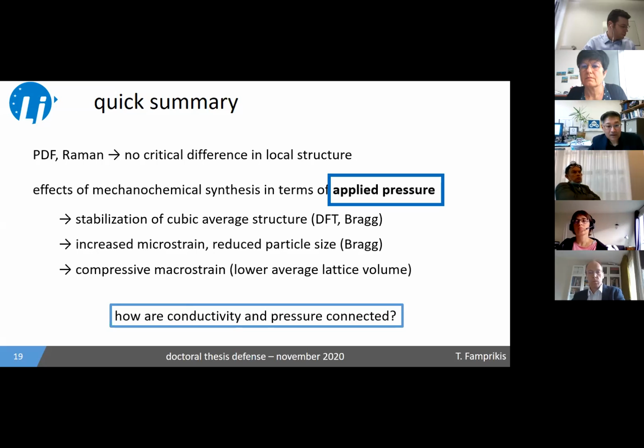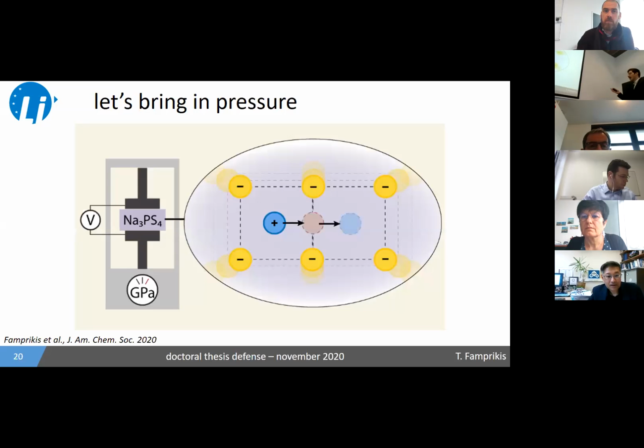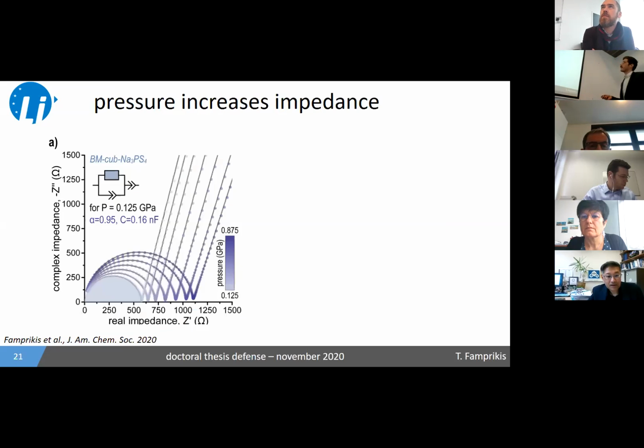And somehow the most obvious thing I could think of is, okay, let's try and measure conductivity as a function of pressure, which is what we do here. We bring basically our impedance setup inside of a uniaxial press, and we measure conductivity as we apply pressure to the material. So the impedance spectra that we get looks something like this.